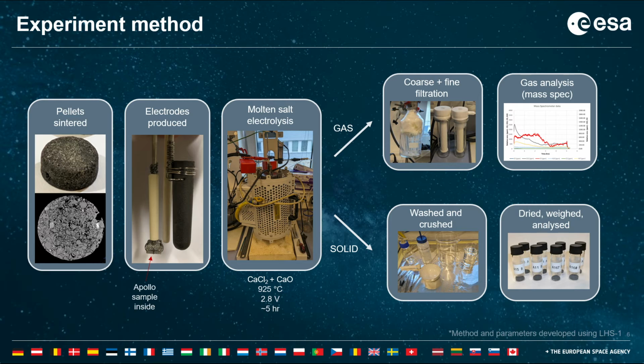So for the molten salt electrolysis, we did this in molten calcium chloride. We found that the process was quite sensitive at the miniature scale, much more than at the large scale. And we chose to use some quite gentle parameters, so only 2.8 volts, and we ran for quite a long period of time. I think it's important to highlight that the